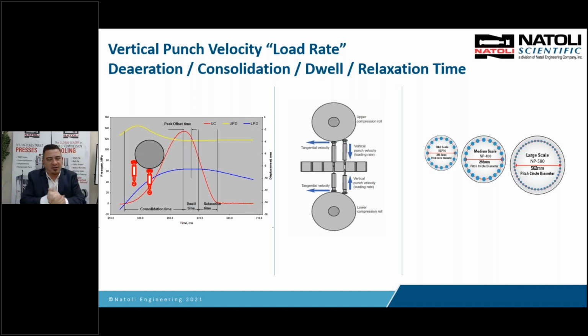But let's say this for an example. Let's say I've got a press with a small roller, and I've got a press with a large roller, but I've got the same head flat for both presses. Say it's a 9.5 millimeter. Well, on a small roll, that punch is going to hit and come down fast, a fast consolidation time, and it's going to have a dwell time that's appropriate for 9.5 millimeter head flat and the velocity.